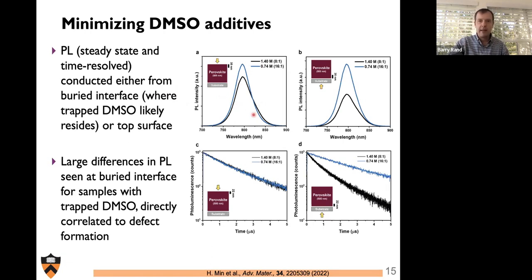And what we see is that the film that has the lower loading of DMSO, there's not a large discrepancy between the photoluminescence output at the top, where most of that DMSO is not present. As you can see, there's about a 10 to 20% difference, but there's about a factor of 2 difference when we illuminate through the substrate, meaning that this bottom part of the film has a considerably poorer quality when you have that DMSO trap there. And we're asserting this is due to that reaction that results in MFA production.